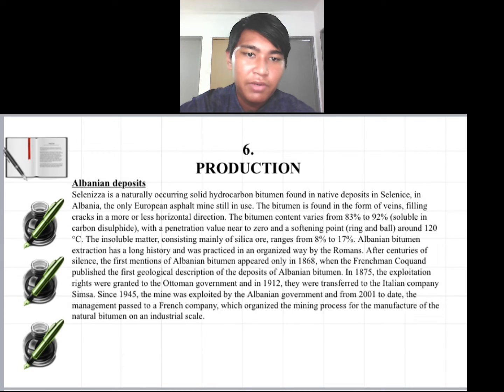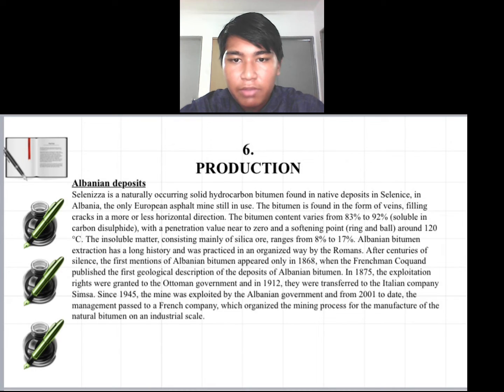The bitumen contains various amounts, from 83% to 92%, soluble in carbon disulfide, with a penetration value near to zero and a softening point, ring and ball, around 120 degrees. The insoluble matter, consisting mainly of silica ore, ranges from 8% to 17%. Albanian bitumen extraction has a long history and was practiced in an organized way by the Romans.